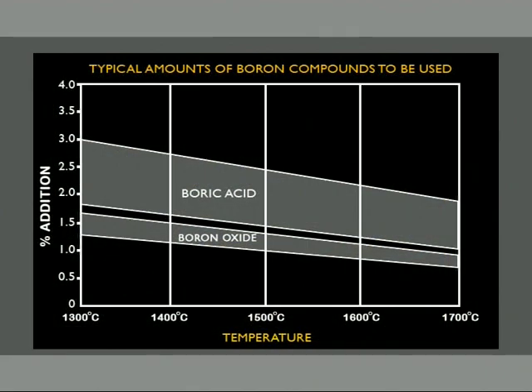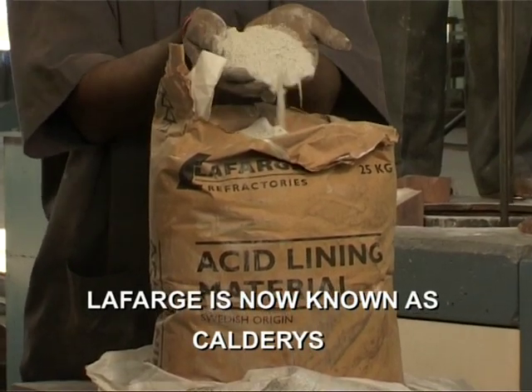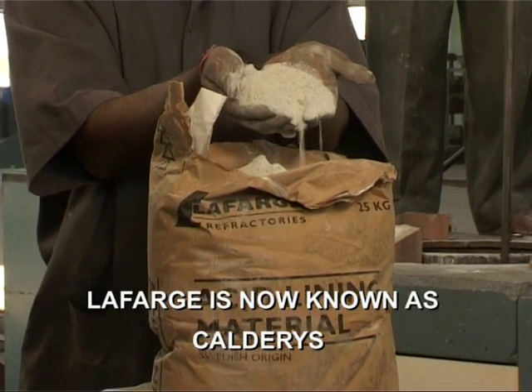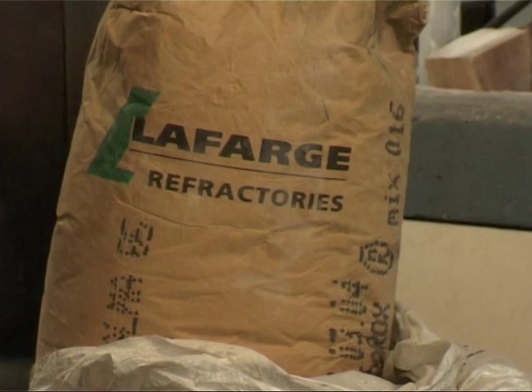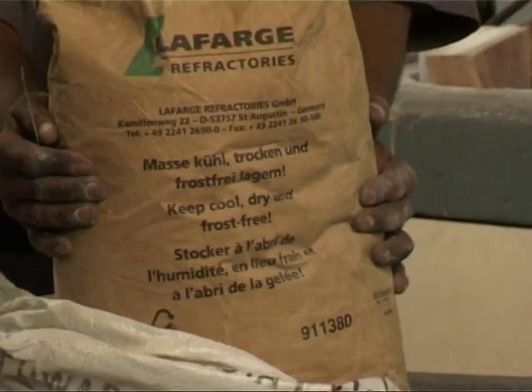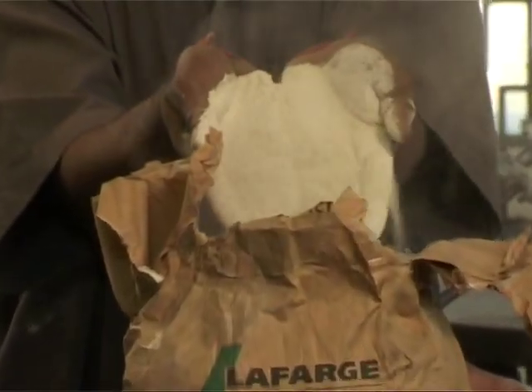Silica ramming mass is available with and without premix binder. The binders commonly used for silica are boric acid and boron oxide. The percentage addition depends on operating temperature, as shown in this graph. This is Swedish quartzite with premixed boron oxide ramming mass. This is alumina magnesia spinel forming dry vibratory ramming mass.